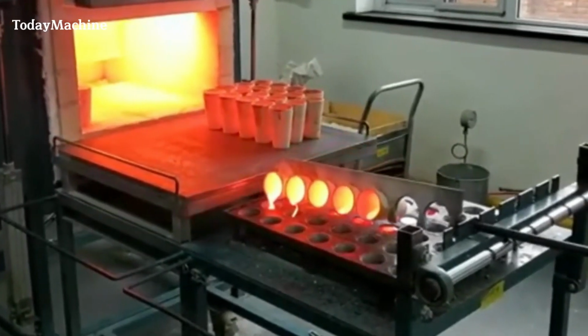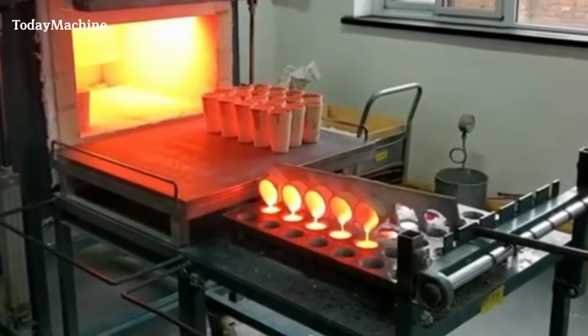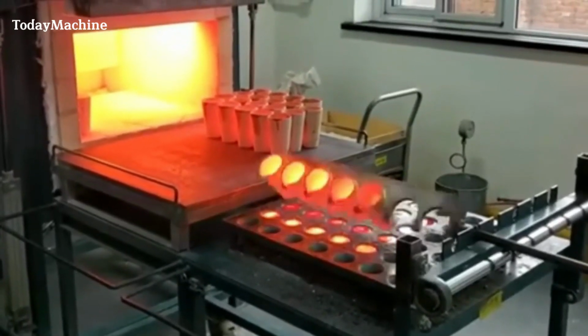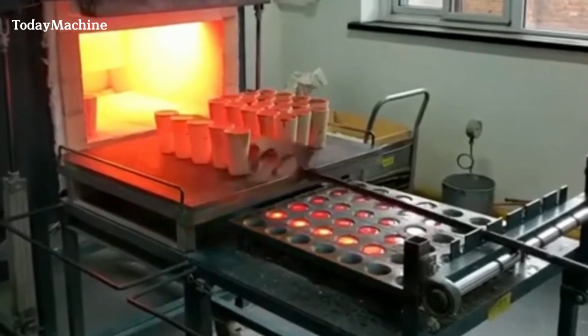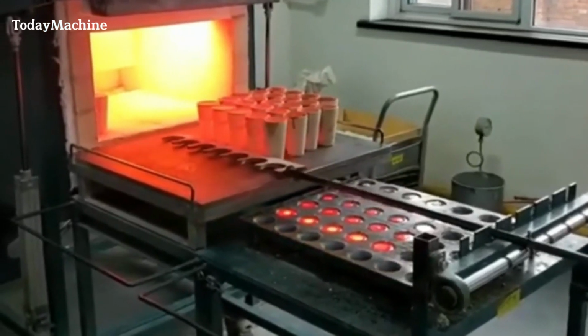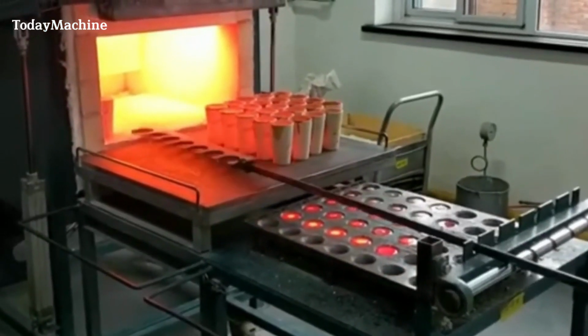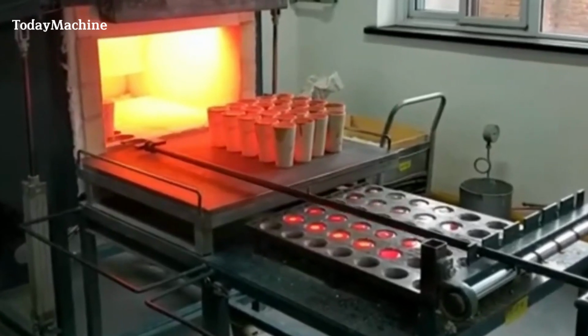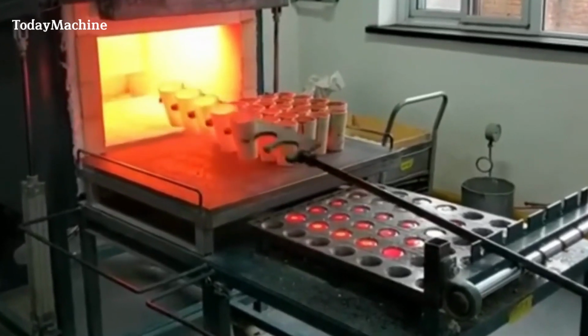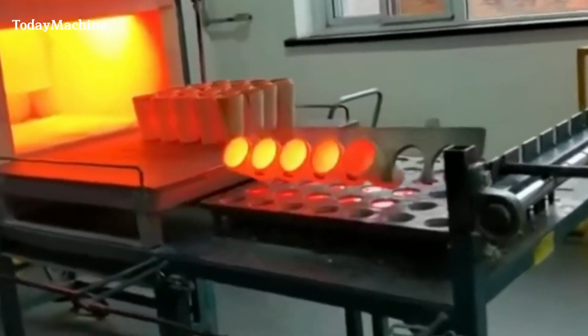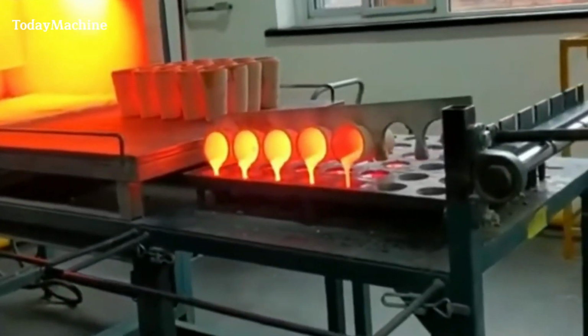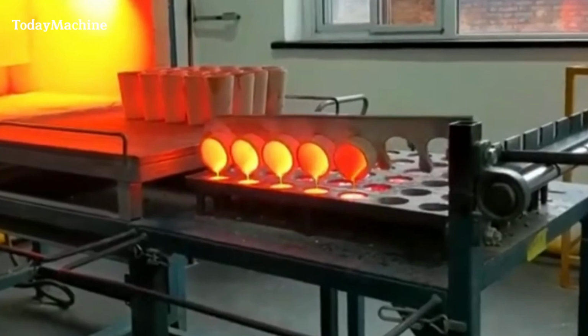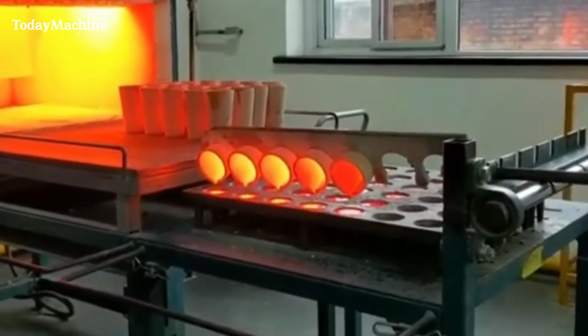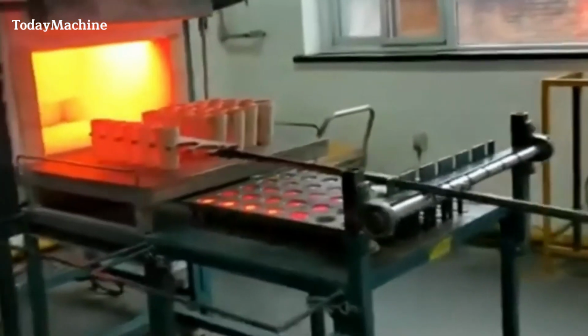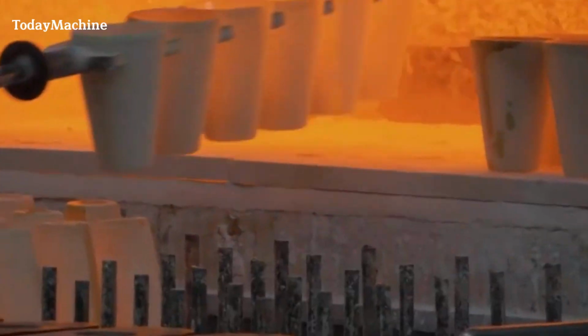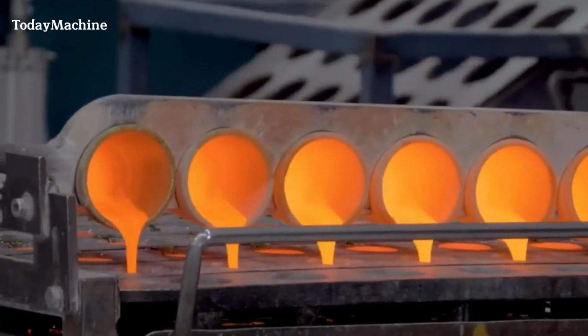Heated in a crucible at temperatures between 1000 degrees Celsius and 1200 degrees Celsius, the flux reacts with unwanted materials, forming a slag that separates from the molten metal. Following fusion, the molten metal undergoes cupellation, a refining step that isolates precious metals. The molten mixture is poured into a porous cupel made of bone ash or similar absorbent material, and heated in a controlled, oxygen-rich atmosphere.